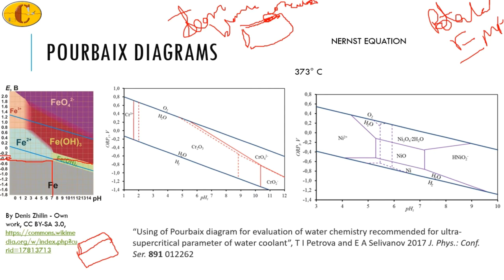Because this is now a kind of passive film, it will act as an active-passive material, which means that it has the susceptibility to undergo pitting and, as a result of the pits formed, stress corrosion cracking. Thus, here the behavior of carbon steel, which will always undergo general corrosion, has now changed to pitting corrosion.